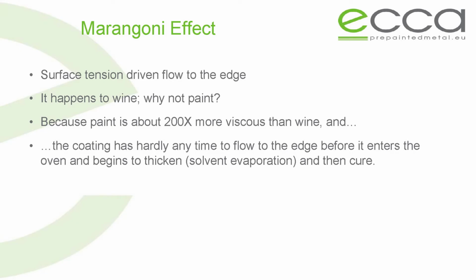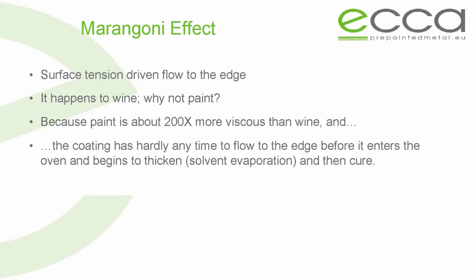And one of the arguments for edge beading was that you put paint on a strip, and just like those tears of wine, surface tension wants to push that paint out to the edge. The problem with that argument is, by the way, now we're getting into causal relationships, okay? We know that edge beading occurs. Now we're debating why does it happen. Wine viscosity is whatever it is, but paint's about 200 times the viscosity of wine. So it's hard for me to imagine that paint is going to get pushed there.